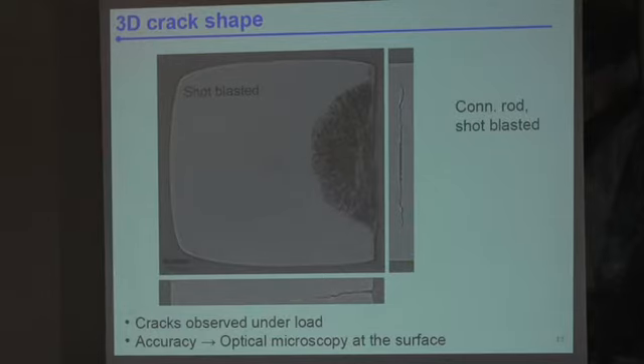So to check the accuracy of the measurement, what we did was to measure the crack length at the surface by optical microscope and check what we had in the tomography, and we got a comparison which was the same, within 1% accuracy, more or less. So we are fairly confident that with tomography we are observing the crack under load, fully open, and that we can indeed detect the crack with a resolution which is comparable to optical microscope.